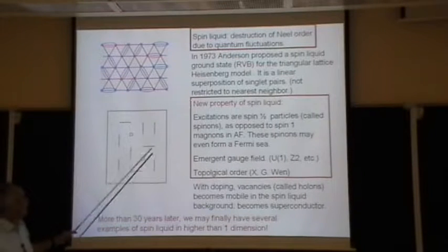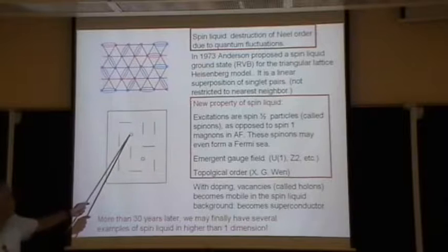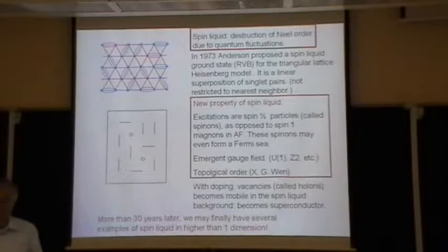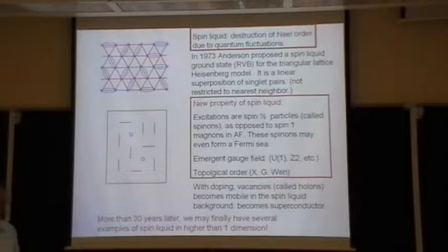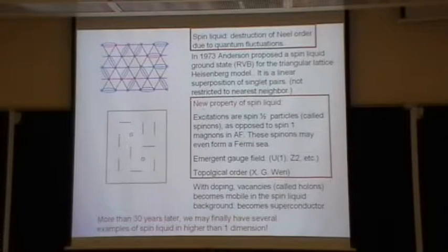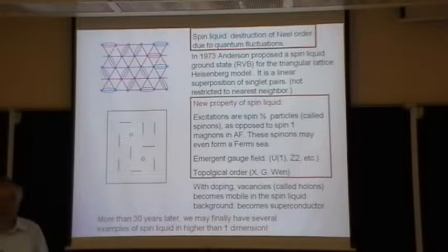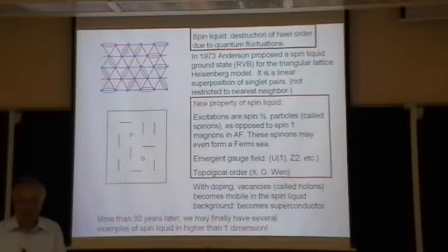So the argument is that the order in the other state is very quickly killed once you dope, because, as I demonstrated in my talk, once you have this dopant, if it runs around, it will totally scramble up your spin. And experimentally, 3% of holes is enough to destroy the order. It's very strong. So the state that emerges after it has been killed by this hole is a very complicated beast, and we don't know how to begin to describe it. So it's not crazy to think that some of these ideas may actually apply once you've scrambled up the spin. So you destroy the order not by frustration, but self-consistently by the holes. The question is whether you end up with something similar. That is, of course, very much an open question.